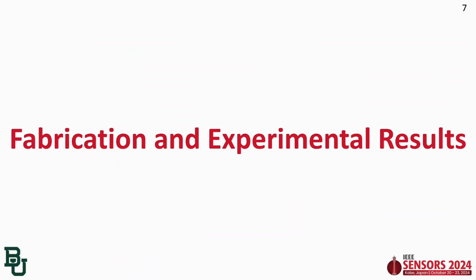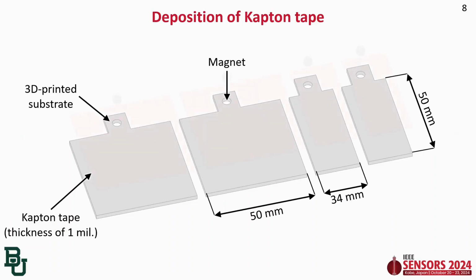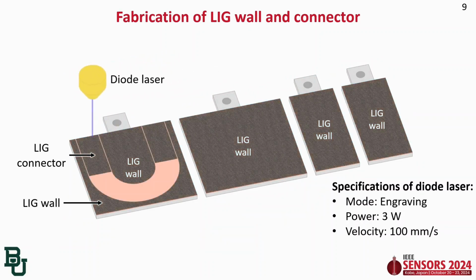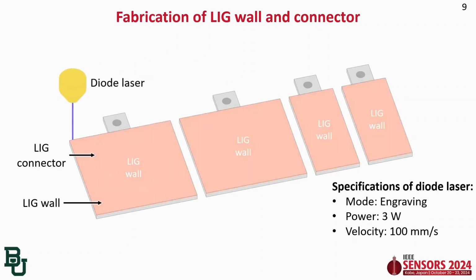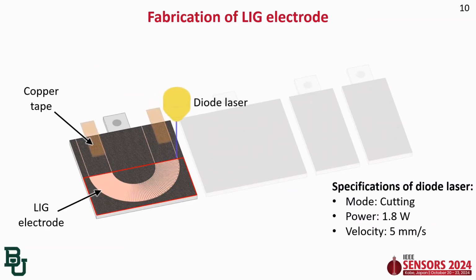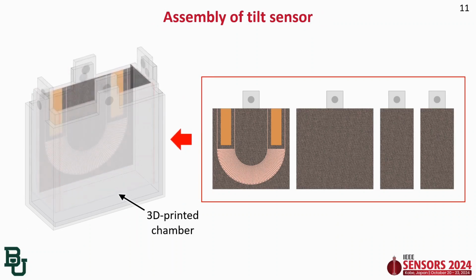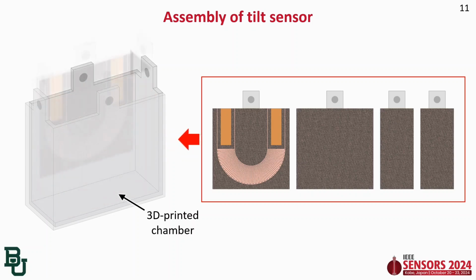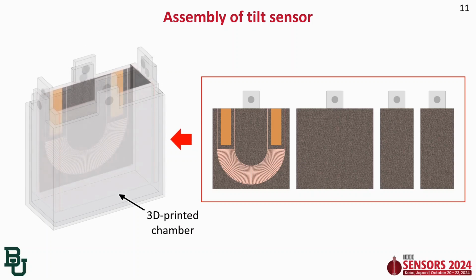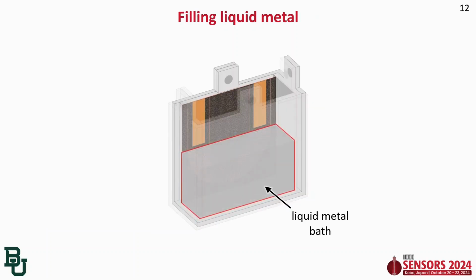Let me talk about how the tilt sensor is fabricated and the experimental research. We use a 3D printed substrate to make a chamber. Kapton tape was attached to the 3D printed substrate as a precursor for LIG fabrication. Permanent magnets were used with each substrate to keep the chamber intact. Then a diode laser is used to fabricate the LIG wall and LIG connector on the Kapton-coated substrate. Next, the serpentine LIG electrode was fabricated on the Kapton-coated substrate. Then copper tapes were attached to the LIG connectors as cathode and anode. The substrates with the LIG electrode, LIG connector, and LIG wall were attached to the 3D printed chamber using permanent magnets. Finally, gallium-indium was injected into the 3D printed chamber by a syringe.